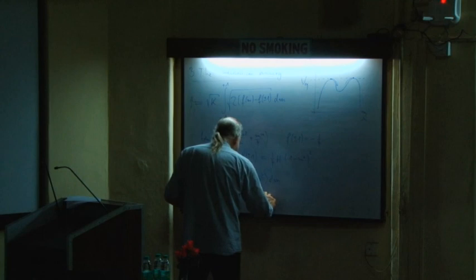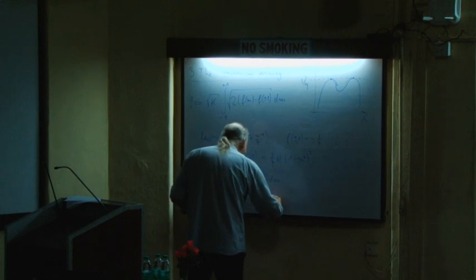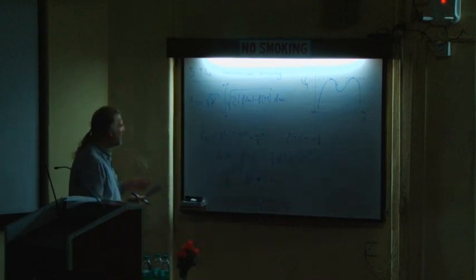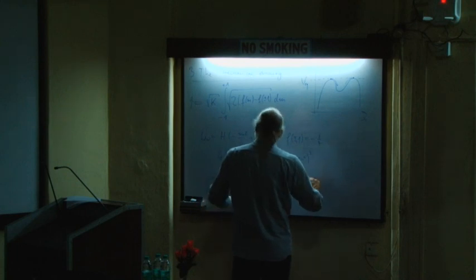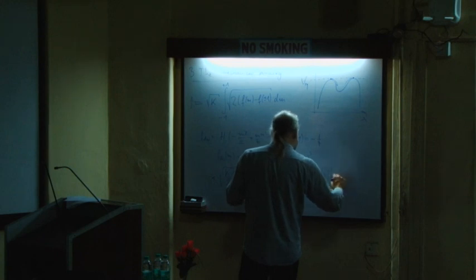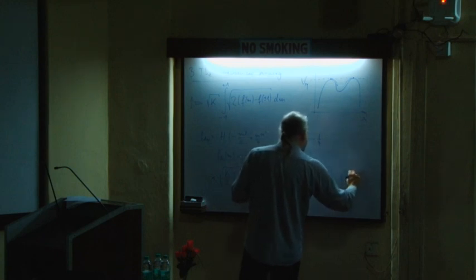This is equal to m minus m cubed by 3 taken between plus 1 and minus 1. So that gives you 4/3, a simple number. So in the end, what you get is that gamma is equal to 2 square root of 2 by 3 times square root of kh.